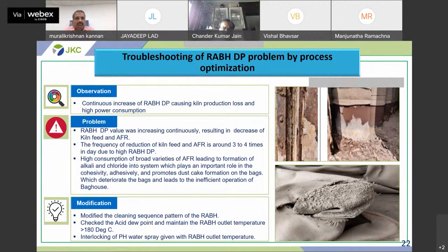The next project is troubleshooting of RABH DP problem by process optimization. Continuous increase of RABH DP was causing kiln production loss as well as increase in power consumption. The RABH DP value was increasing continuously, resulting in decrease of kiln feed and AFR. The frequency of reduction was around 3 to 4 times in a day.